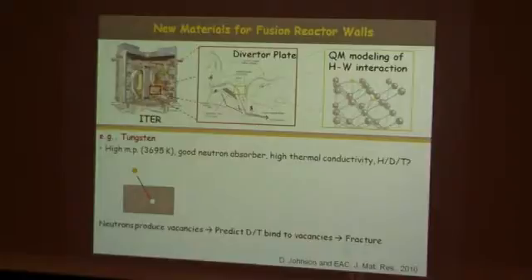That's a big problem. It also turns out that hydrogen tends to embrittle metals. And as a result of that, you could end up with basically cracking of the whole instrument. So that would be a big problem. But it turns out that in the presence of vacancies, hydrogen and its isotopes love these vacancies, and they go and collect at these vacancies.